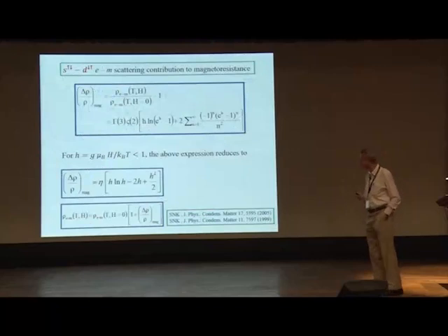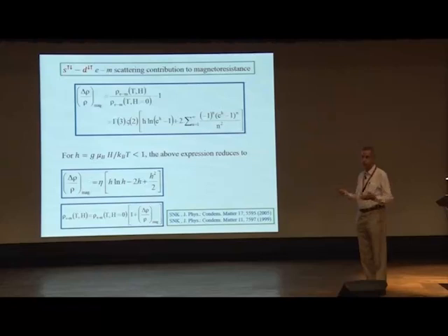Now I go to the magnetoresistance. Here, as we know, other contributions, such as electron-phonon, you don't expect to get reflected in magnetoresistance. It will be only the electron-magnon part. And out of that electron-magnon scattering, it is basically the so-called spin flip interband sd scattering which actually gives rise to the magnetoresistance.